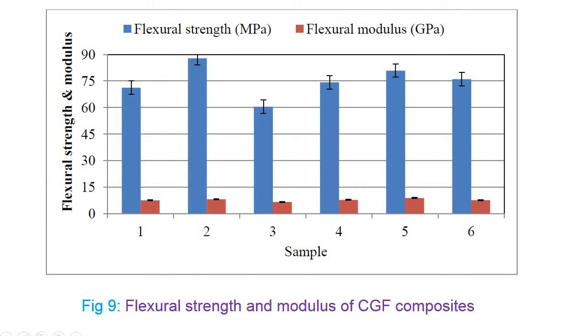When I am going for the test, I will take the flexural test. For that I will get 2 data. One is the flexural strength. You can see the figure. The flexural strength varies from 60 megapascal to 80 megapascal. You can see that there are 6 samples. We are taking 6 samples from a single composite plate, with nearly 60 megapascal to 80 megapascal varying. You can see the graph and get it in a very clear manner.